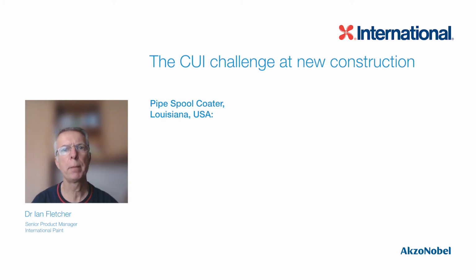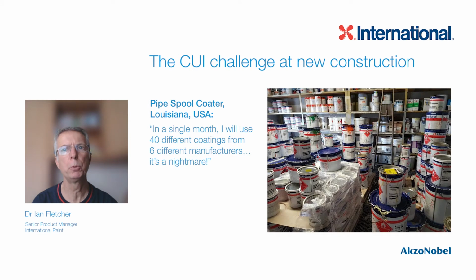And if you add different colors and pack sizes, a typical pipe spool coater's storeroom can start to get very complicated. A pipe spool blaster and painter needs to know how many different coatings are required, which spools need insulation and which ones do not, which ones are for cyclic service and which ones are not, and then how many different coating systems are needed. This segregation into each coating category is critical in order to avoid making mistakes and using the wrong coating system on the wrong pipe spool.